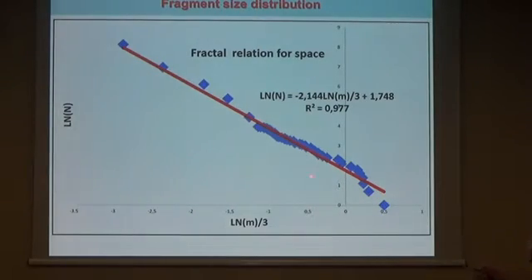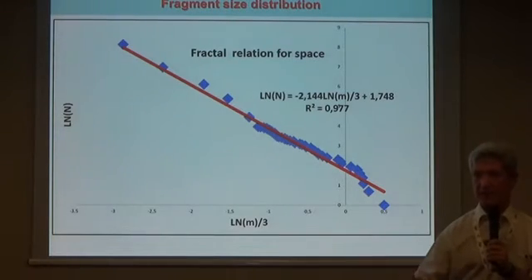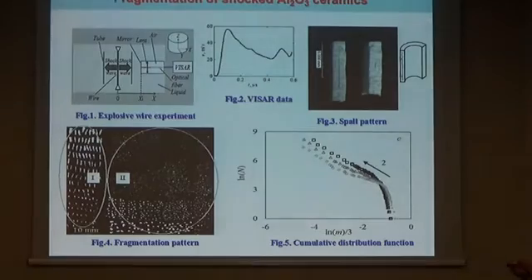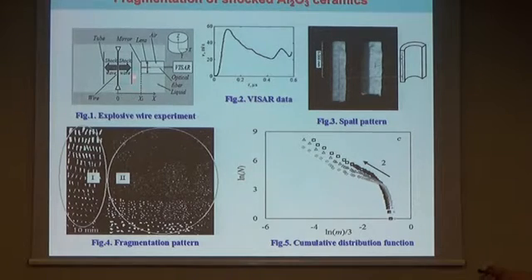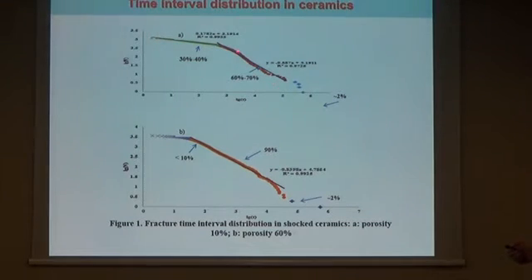And when we processed the data as a spacing between the signals, we obtained, for instance, concerning the characteristic scale of the material, a very pronounced power law that exactly corresponds to criticality due to the numerous generation of these similar modes. Practically similar results were obtained for ceramics, but with the goal to save the fragments. It was the experiment when we had the fragmentation due to the shock in ceramic rods in liquid. And practically similar power laws were obtained for ceramic, depending on the density and depending on the initial porosity. And this point of breaking in these plots is very important because it separates the absorption ability of ceramics depending on the initial porosity.